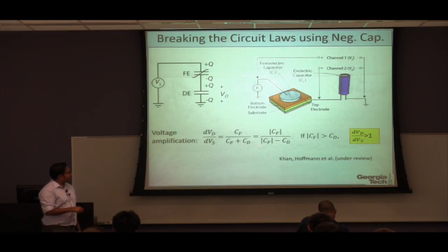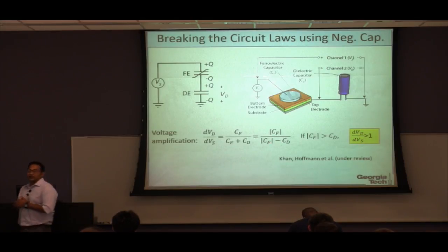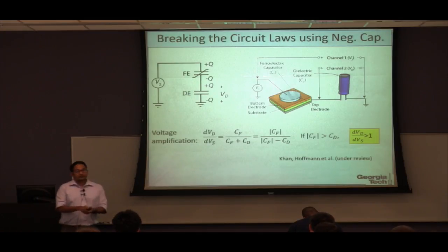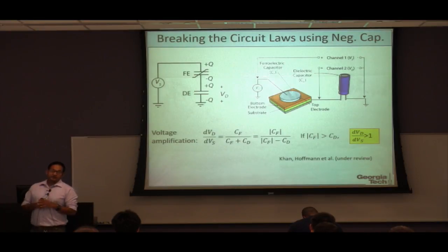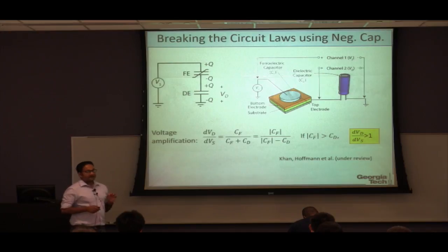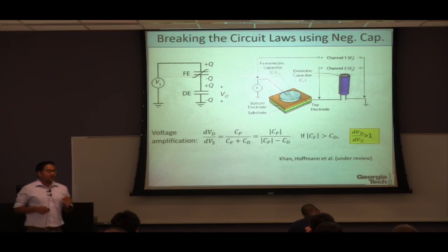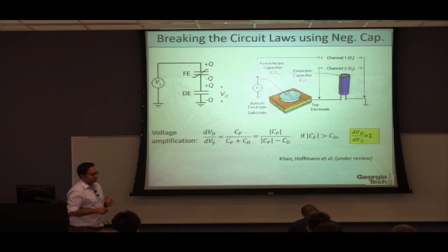But if one of the capacitors is negative, then this ratio will be larger than 1. And this means that you can get a small signal amplification in a purely passive network. Now, note that in any network of two similar passive elements, you can never get an amplification. But in this case, because one of the capacitors is negative, you can get a voltage amplification.